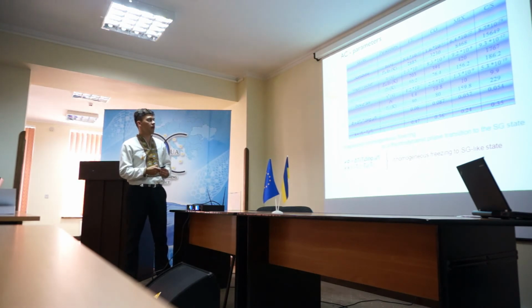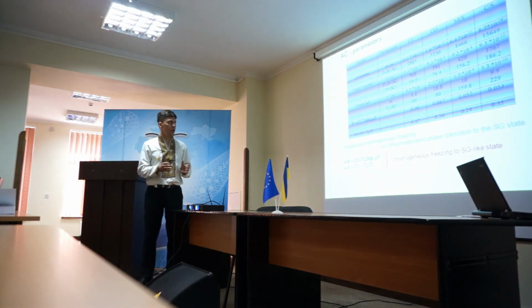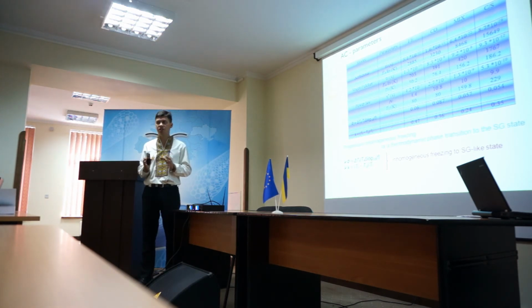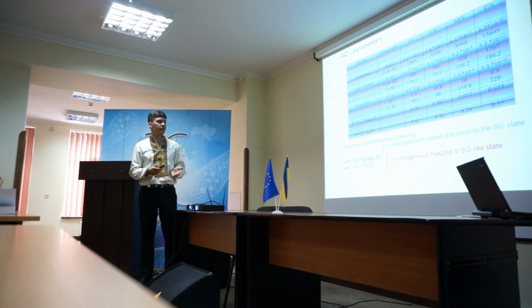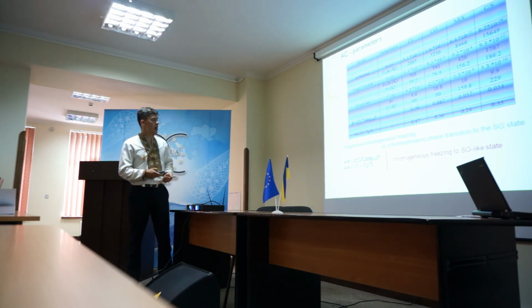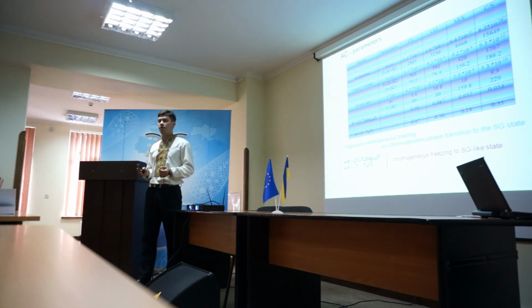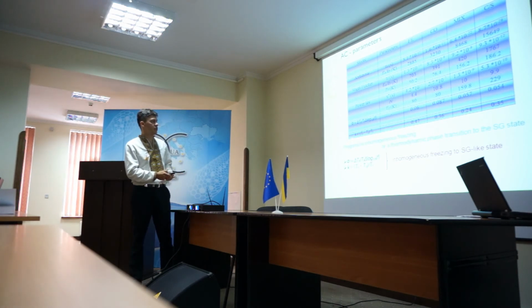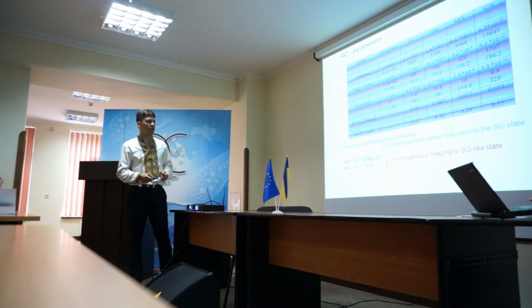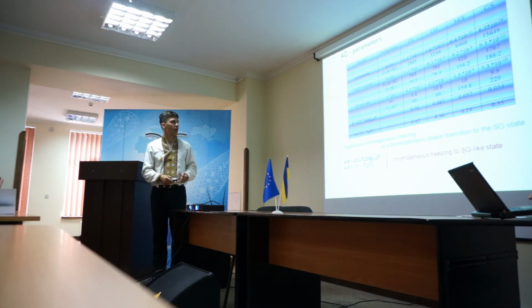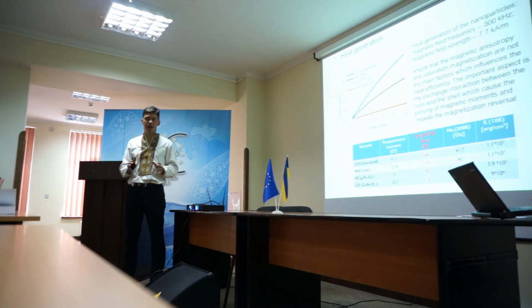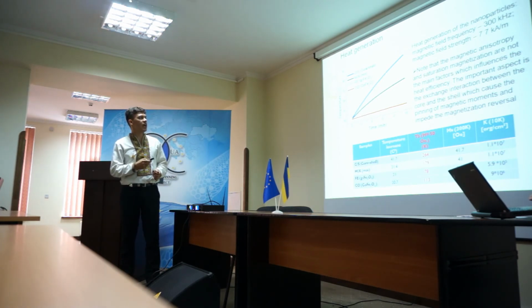Then we use the Vogel-Fulcher law and the power law. These are used for nanoparticles with some interactions, and we obtain physically reasonable values for all samples. And this means that we have two possibilities. It can be a progressive inhomogeneous freezing or a thermodynamic phase transition to a spin glass state. To answer this question, we use these two empirical equations, and the obtained parameter is typical for inhomogeneous freezing to a spin glass-like state.